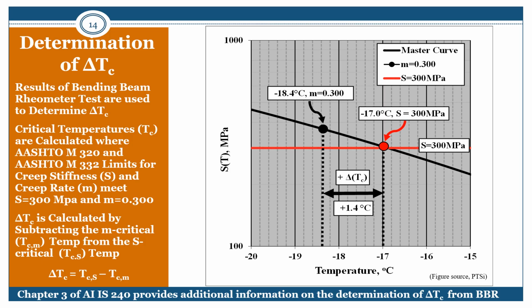The critical temperature, T sub C, for both creep stiffness, S, designated as T sub CS, and creep rate, M, designated as T sub CM, are determined at the specified performance grade, PG, limits according to AASHTO M 320, performance grade binder specification, or AASHTO M 332, MSCR performance grade binder specification. Conditions and limit values are 300 megapascals and 0.300 respectively. Delta TC is then calculated by subtracting the M critical T sub CM temperature from the S critical T sub CS temperature.